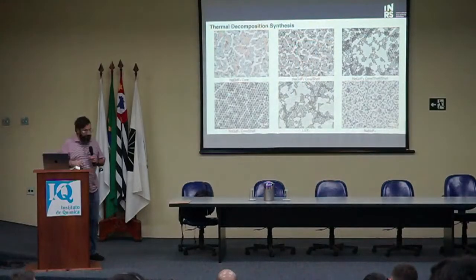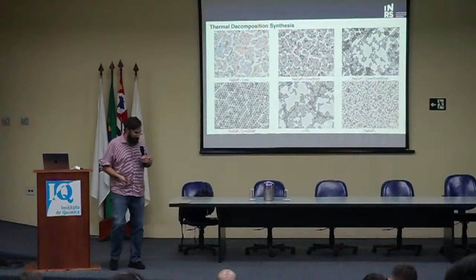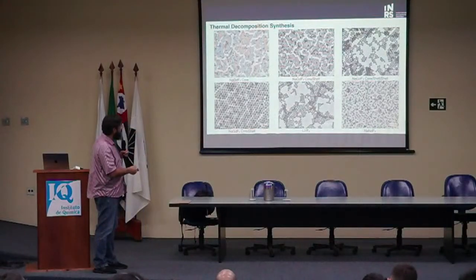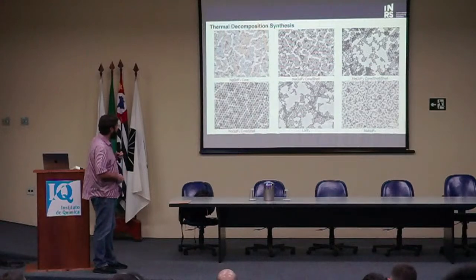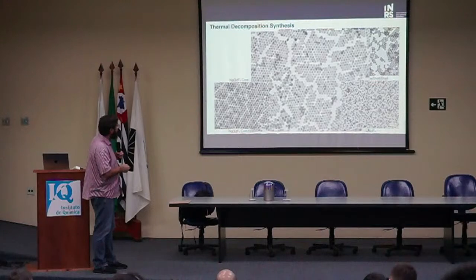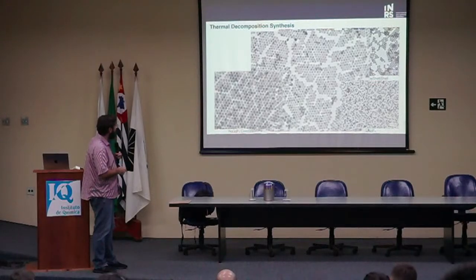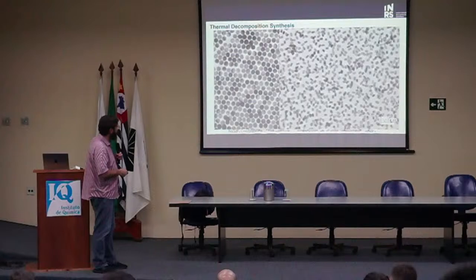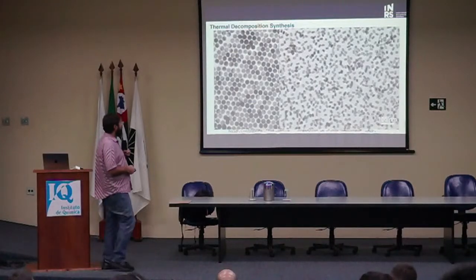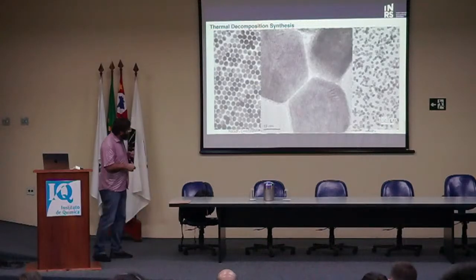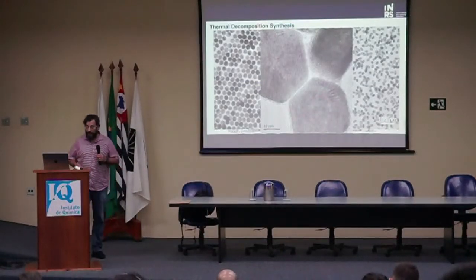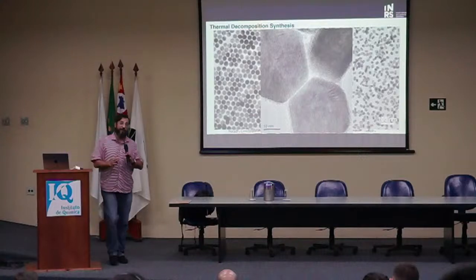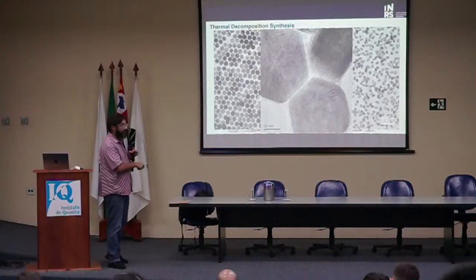And just as an example of the type of nanoparticles we can make, again, we have very strict control over the morphology and over everything, size of the nanoparticles, so we can make hexagonal particles, we can make spherical particles, we can even make short stubby nanorods. We've made longer nanorods after that. But it's important to point out that they're all very crystalline, okay? But not only are they crystalline, it's also important to notice that the particle size is very uniform.